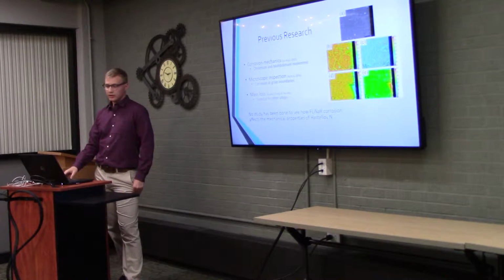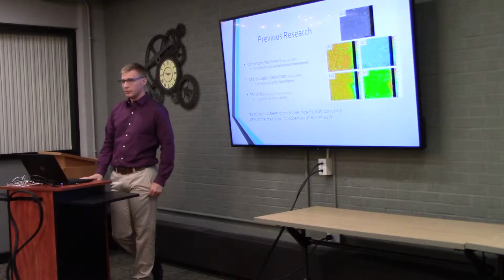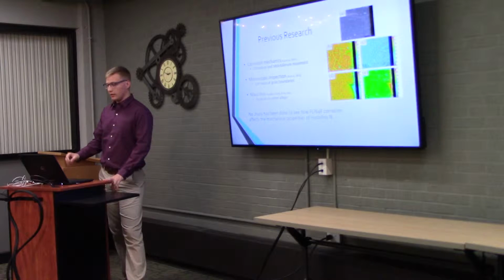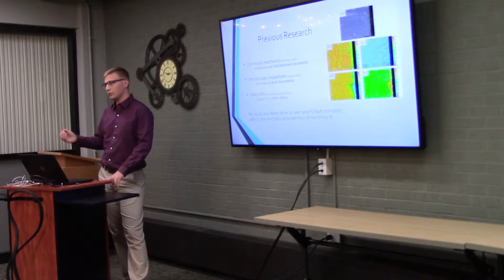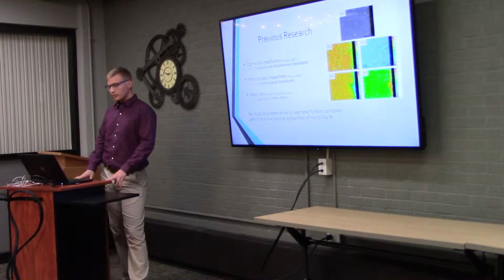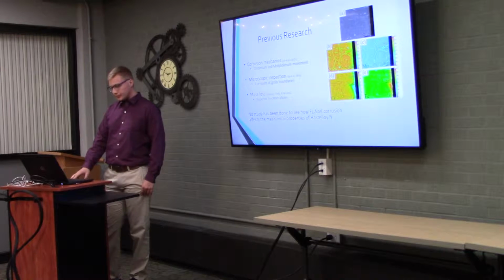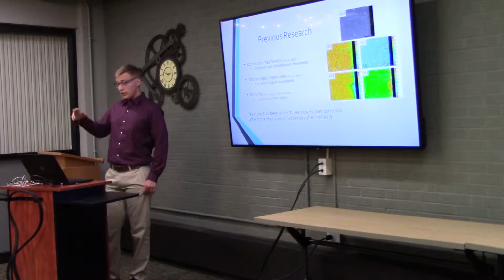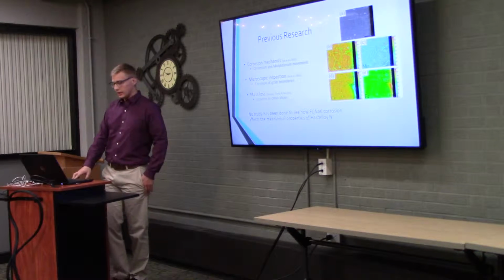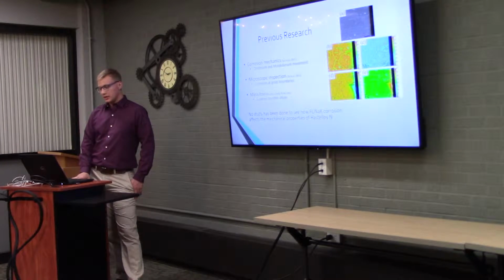So previous research that has been done using FLiNaK and Hastelloy N: one study looked at the corrosion mechanics between these two substances. The main way that the corrosion happens is the FLiNaK will actually draw the chromium and molybdenum that is in the Hastelloy N to the surface, and then it'll eventually diffuse into the salt. Another study found that the FLiNaK corrosion occurred mainly at the grain boundaries of the Hastelloy N. And another study did a mass loss test and found that the Hastelloy N was more resistant to FLiNaK corrosion than other alloys that they tested it against. However, no study has been done to see how the FLiNaK corrosion affects the mechanical properties of Hastelloy N.